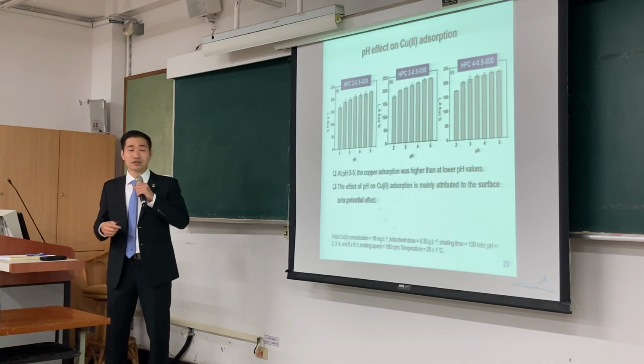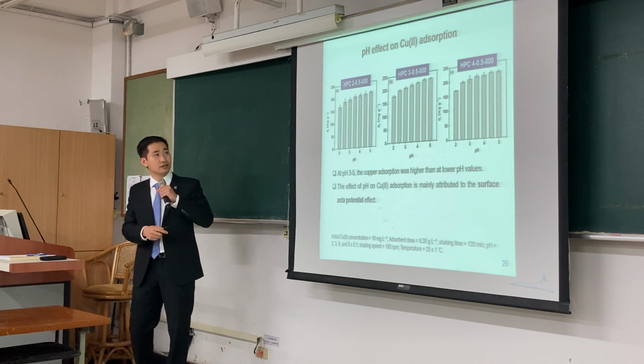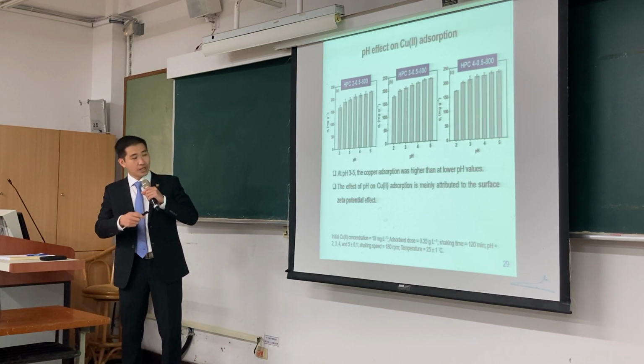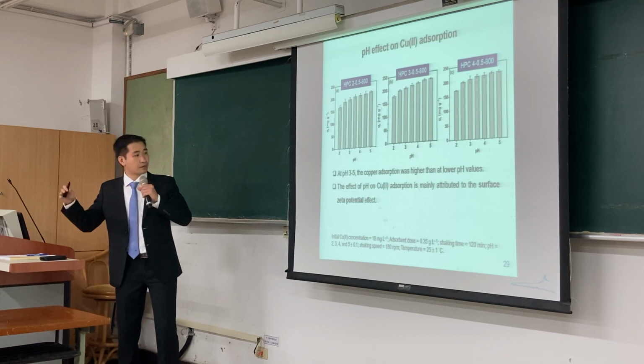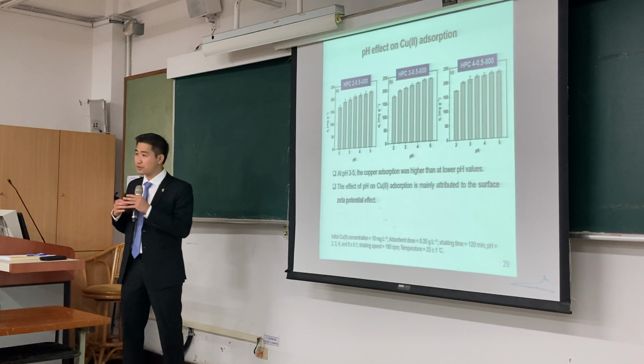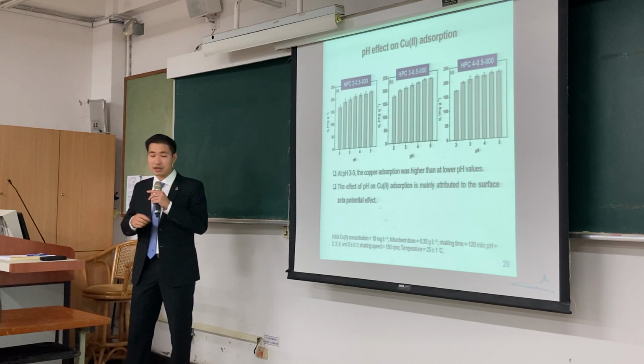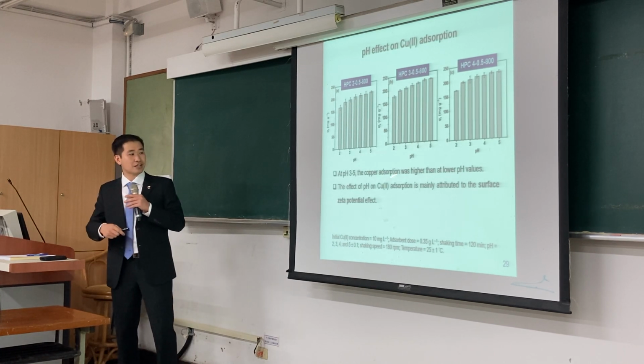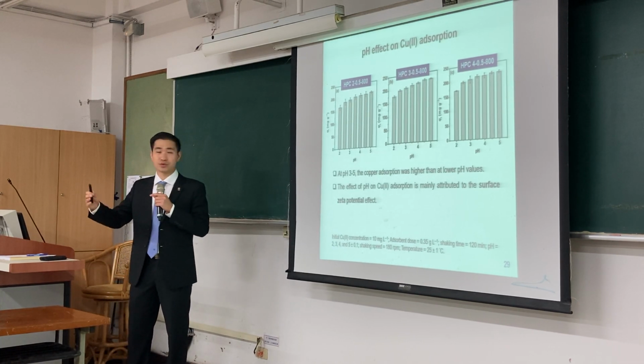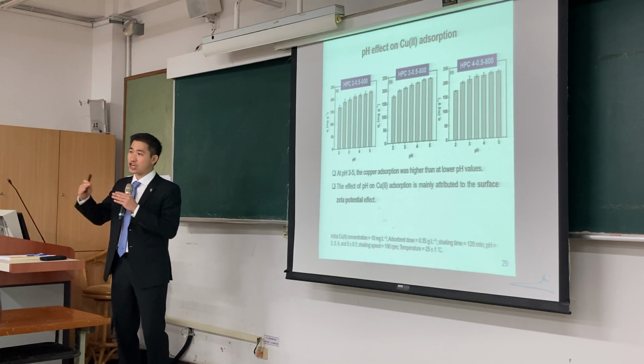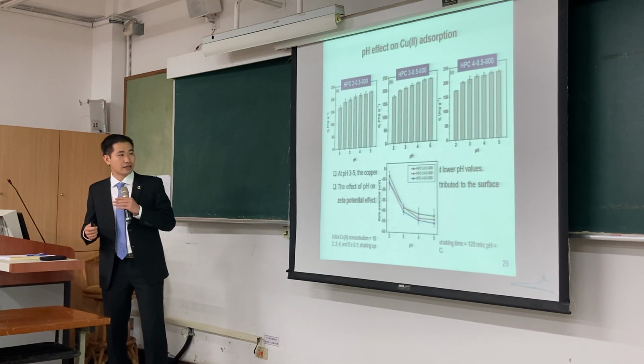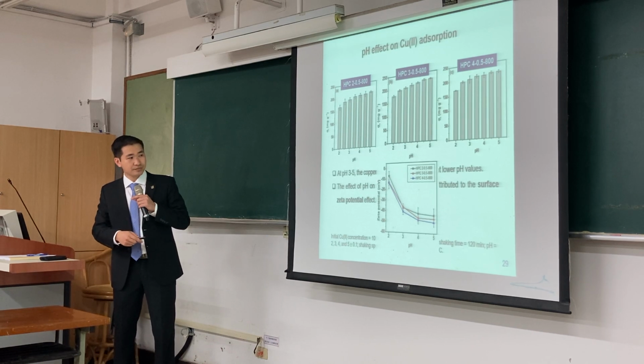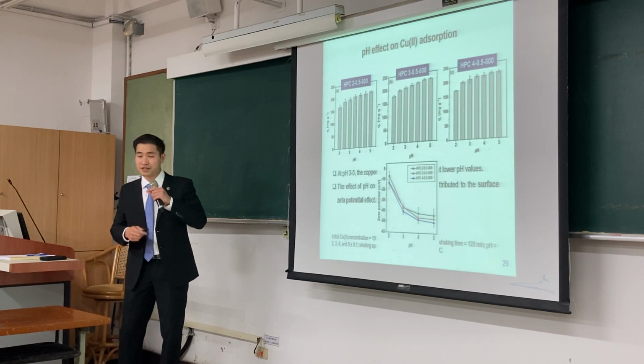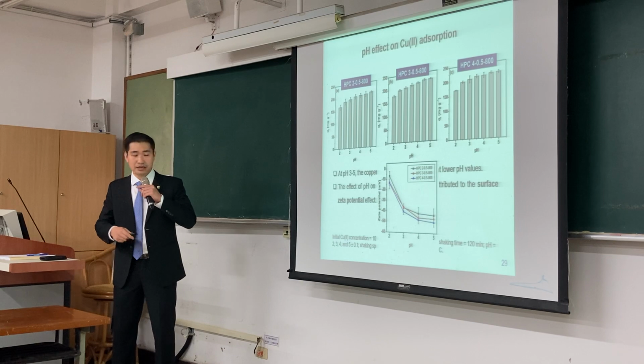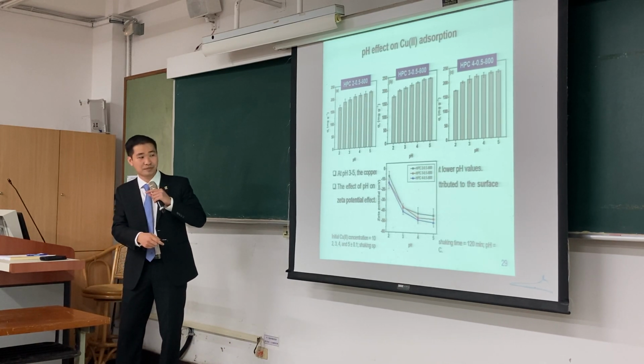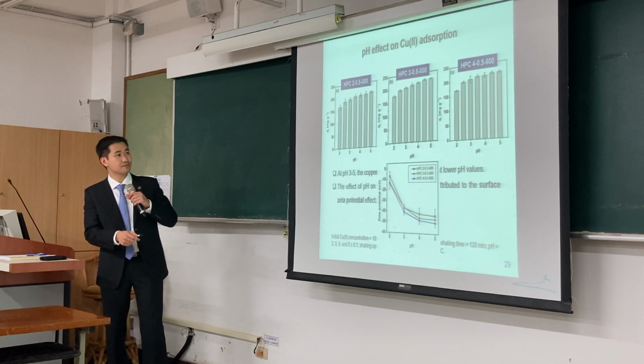The pH effect on copper adsorption was conducted. We can see at pH 3 to 5, the copper adsorption is higher than at low pH. The effect of pH on copper adsorption may be due to the surface charge. As mentioned previously, at pH 3 to 5, the material is highly negatively charged compared to low pH.